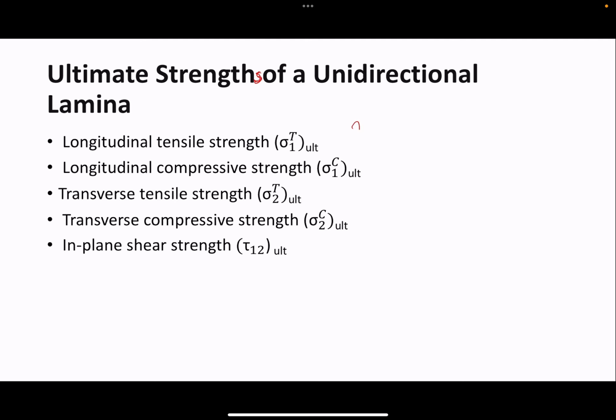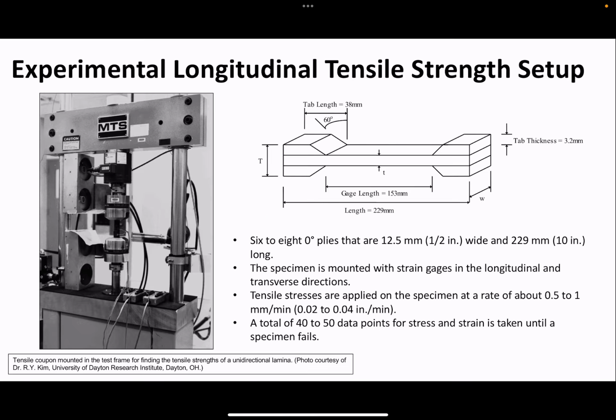So, in direction 1 along the fibers, you have 2 different strengths. Longitudinal tensile strength and longitudinal compressive strength. They are not equal. So, you have 2, and similarly perpendicular to the fibers in direction 2, you have 2 strengths, transverse tensile strength, transverse compressive strength. And of course, you have the in-plane shear strength. Maybe I should not draw this. This is 1, 2. Note here that we do not talk about out-of-plane load. It's more complicated. Okay. So in this pre-class video, you're just going to see experimentally how these values are obtained.